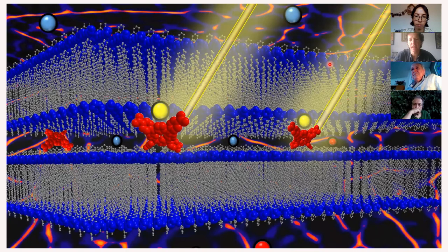Yeah, and related to that, he says, if there is, which is the minimum diameter that could be achieved? I don't know. Minimum diameter. So yeah, that's a really interesting question. I think one of the things which surprised us about this gel system was that in the AFM, I don't know if you recall, with the 9:1 solvent mixture, we actually showed this kind of structure where we just had two bilayers, one on top of the other, which I think is a really interesting opportunity in terms of nanoscience, to be able to do that. I don't think it's something people have looked at an awful lot, but in terms of this dimension, the height of those fibers, we've shown one or two bilayers. Normally it would be a few more.